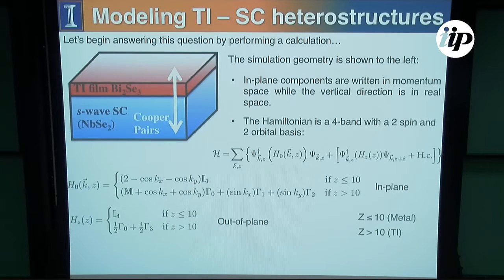The reason that we chose 4 quintuple layers for this particular structure is because this was the system that we had primarily results for that were experimental, and so we thought it would be a much more interesting paper if we actually tried to simulate the exact same system. So the out-of-plane components, again, we have the metal components here, which is nothing interesting, and the out-of-plane components for the topological insulator.